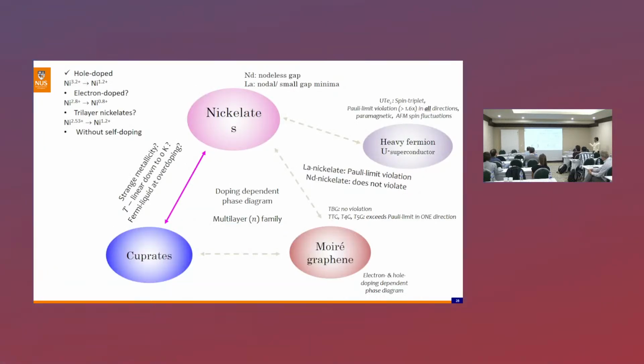Well, just to conclude, there are differences, and of course there are similarities with the cuprate, but it's not just limited to the cuprate. We also notice this violation of the critical field, so you need to learn more from the heavy fermion system, as well as this Moire graphene, which has some similar features. So more things can be done, for example, to try to produce a system that is dominantly electron doped in the case of superconductivity, as well as, of course, producing bulk superconductors, and then probably a new system without the self-doping that probably creates differences with the cuprate that we observed so far, to make it more pure and closer to what we have in the case of the cuprate.